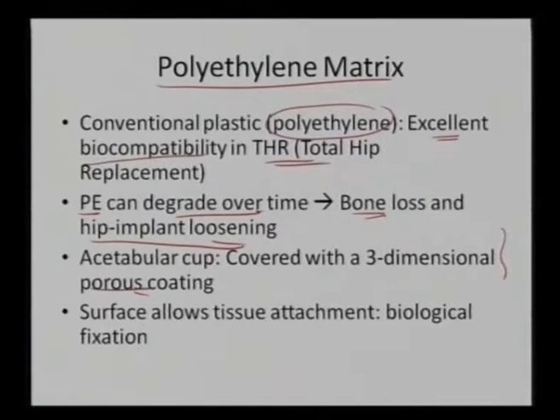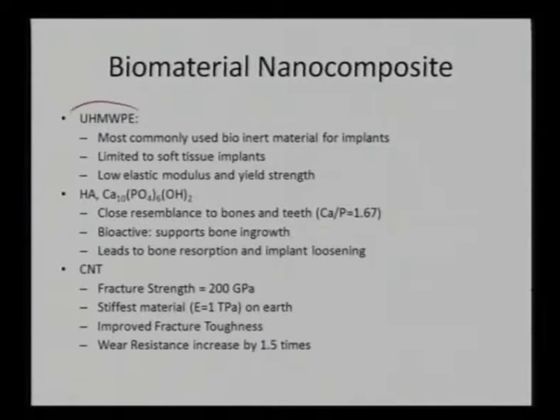At the same time, polyethylene can also allow for tissue attachment or biological fixation. That is one more advantage of polyethylene: it can allow tissues and cells to grow onto its surface. In this particular component, we are utilizing ultra high molecular weight polyethylene because it has shown to be exceptionally cytocompatible in total hip replacements, and it is a very commonly used bioinert material for implants. But the problem with this polyethylene is that it is limited to only soft tissues. Because of its lower mechanical properties, it is limited to soft tissue implants, and at the same time it has a very low elastic modulus and low yield strength.